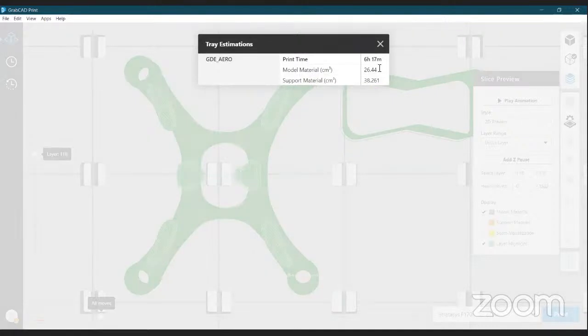Now, even if you see the estimates here, when we chose the first setting at 23% infill and the smart support structures, it was taking about 5 hours. When I change the infill density and the support density, without changing the dimensions of the object, without scaling it down or up, it changes the printing time, and it also changes the consumption of material. Since I'm using the surround support structure option, it is consuming much more support material than the previous.